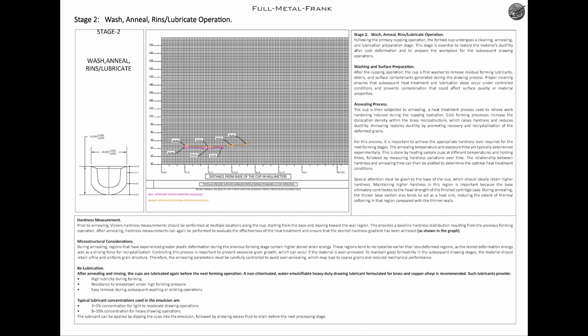The annealing temperature and exposure time are typically determined experimentally. This is done by heating sample cups at different temperatures and holding times, followed by measuring hardness variations over time. The relationship between hardness and annealing time can then be plotted to determine the optimal heat treatment conditions.